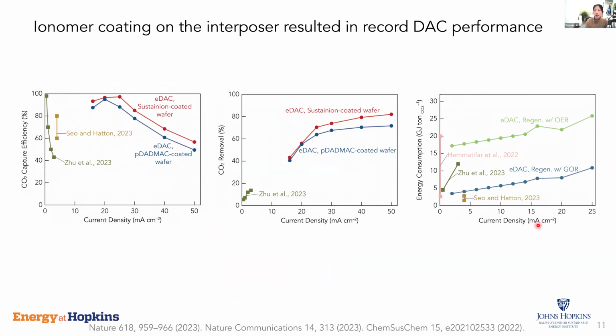And if you look at the energy consumption, if we pair our PCET mediator regeneration with oxygen evolution reaction, because of the higher overpotential of oxygen evolution reaction, the energy consumption is on the higher side. But alternatively, we can pair our regeneration with an alternative oxidation reaction. In this case, we're oxidizing biomass into value-added products, and that can substantially lower the energy consumption while giving us an opportunity to generate beneficial co-products.